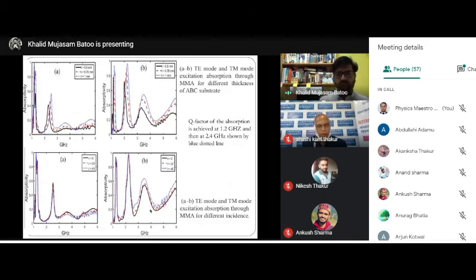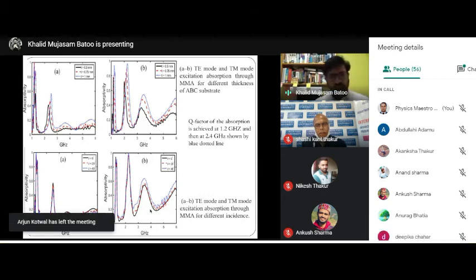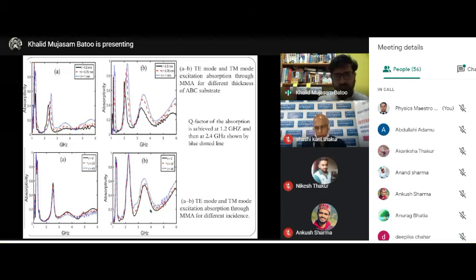So what we did, we studied the TE and TM modes, which are transverse electric and transverse magnetic modes of the material, in order to see how this material can be utilized in a higher frequency range as an absorber. The absorption shows that this material has good absorption up to 2.4 gigahertz, shown by the blue dotted lines in transverse electric mode.